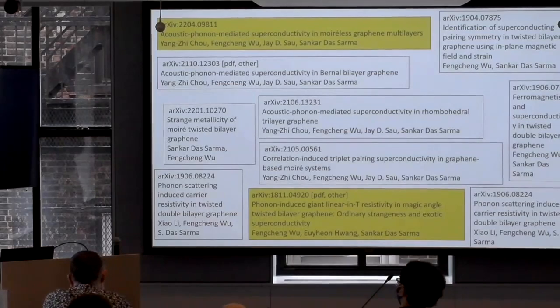But if you look at the raw numbers, first, this statement that it is linear down to very low temperature is very misleading in two ways. One is that it is linear down to very low temperature in very high magnetic field. Now, I'm not saying magnetic field will change the phonon structure very much, but that's not the system we are talking about. Second, many experiments do not see linear down to very low temperature. People just quote the ones which do. I have looked at 500 resistivity papers. In some, it doesn't go to very low temperature. In some, it does. It's definitely not universal.